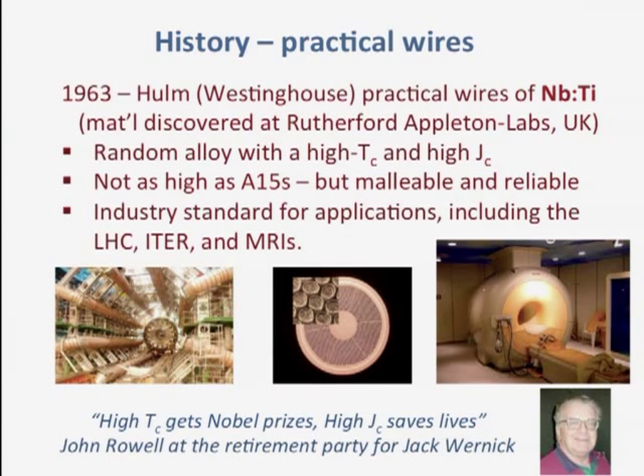If you have a random alloy, like niobium titanium, it's malleable, right? These compounds tend to be brittle. The alloy is malleable, and it's hard to screw up the TC. So the TCs aren't as high as the A15s, and the critical current and critical fields aren't as high as the A15s, yet these are the workhorses for the field.